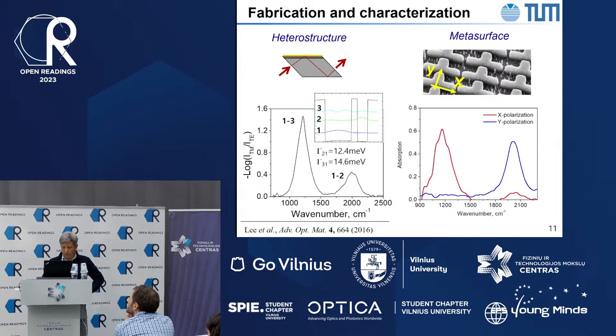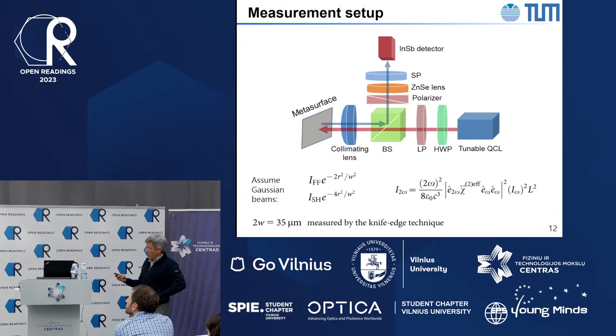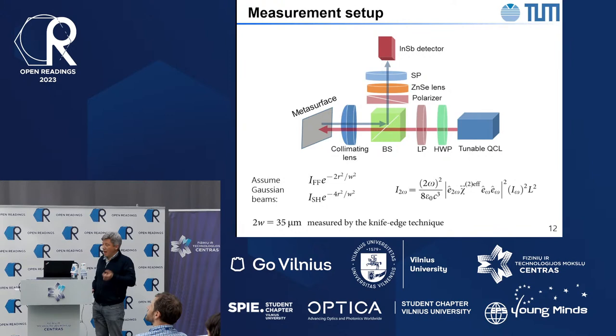And then we could use a semiconductor laser, which is a quantum cascade laser that is similar in operation to this red laser pointer. It has actually similar amounts of power. This laser pointer is probably something like 5 milliwatts, and the QCL is 50 milliwatts. So we really have a continuous wave intensity comparable to this laser pointer and a deeply nonlinear metasurface, which was lambda over 20 in thickness.